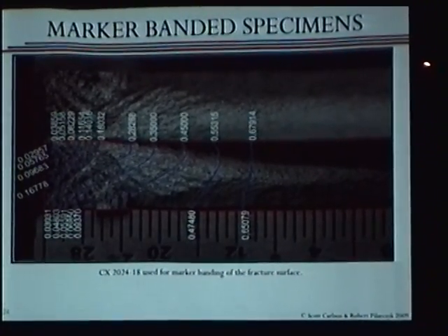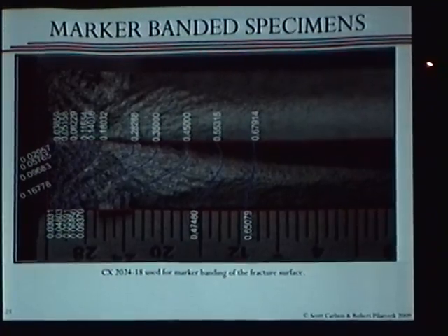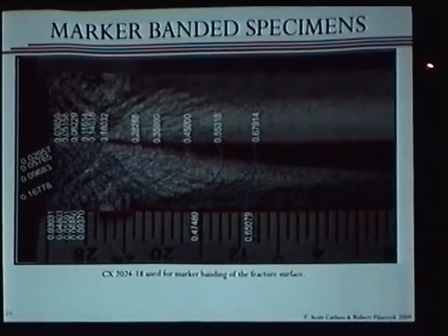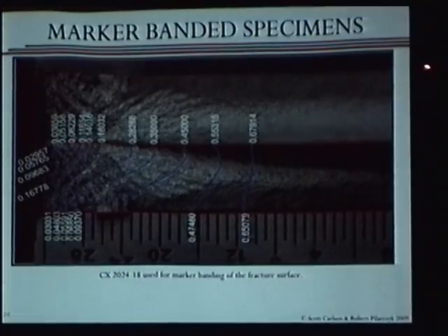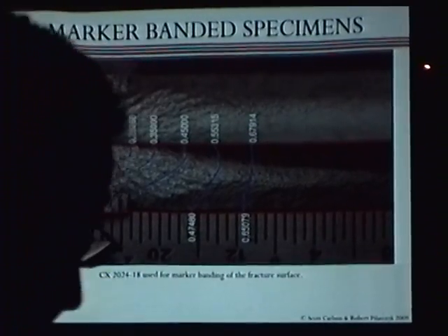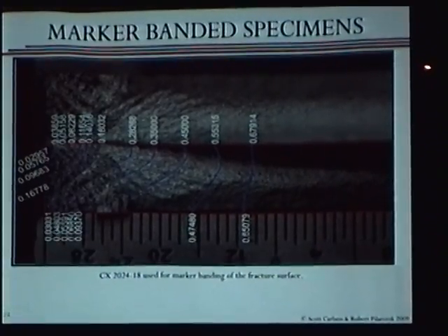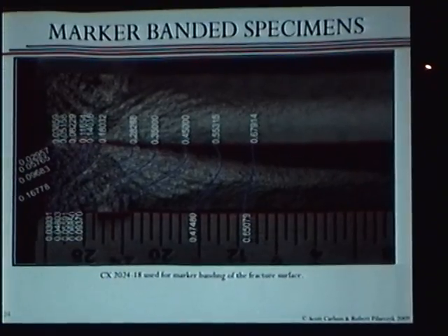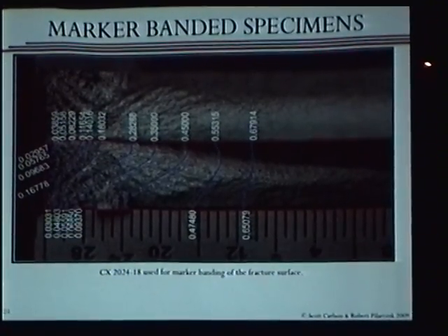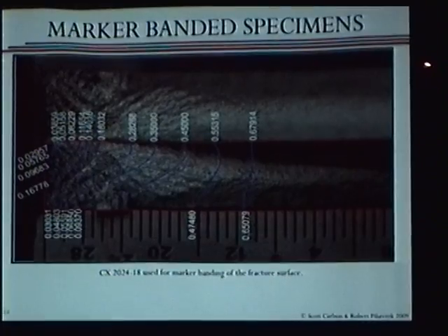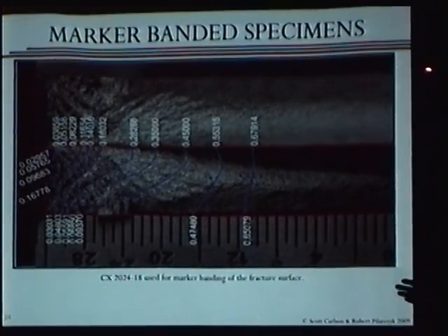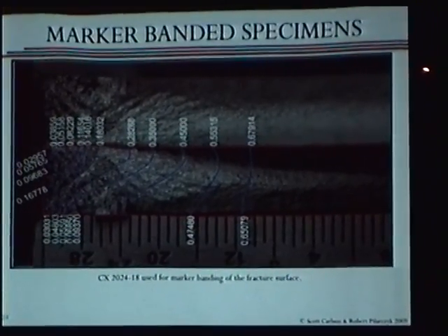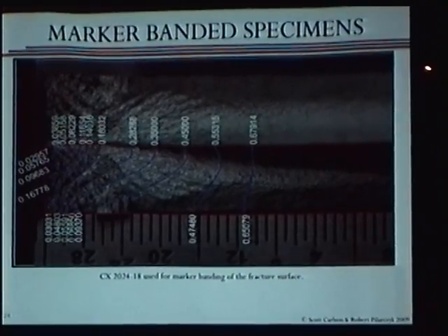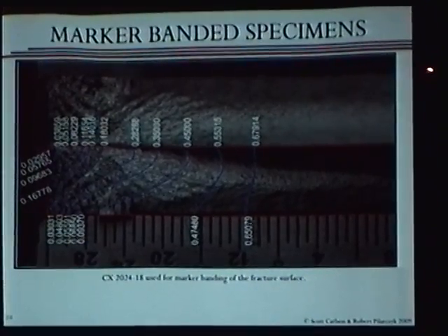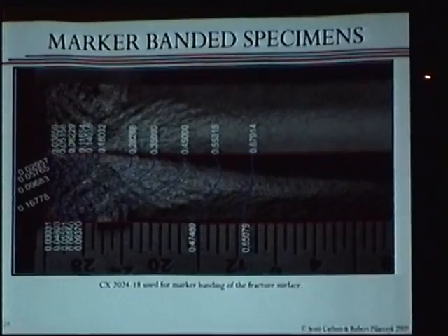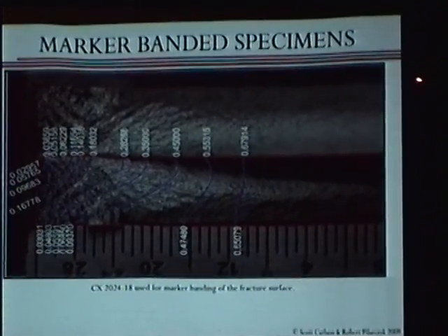And it's very odd, and it can really cause a lot of problems if you're developing an inspection. If you're an NDI guy and you go out and say, I want to inspect a spar cap in a wing box, and I don't want to take the fastener out, I just want to do a surface scan inspection, because say I've got a whole row of fasteners that I want to look at. If I have to pull out all those fasteners, it's going to be a lot of work. But if I just do a surface scan, that's great. Maybe I can see a crack that's acceptable, and it's a lot easier inspection.